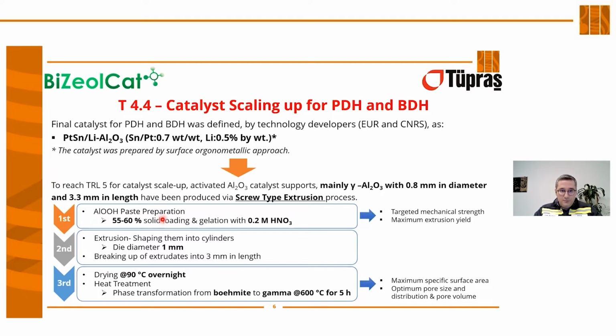Our first step is the preparation of the paste. This contains Boehmite particles, and we change the solid loading and the gelation ratio with nitric acid concentration in order to increase the mechanical strength and reach the maximum extrusion yield.